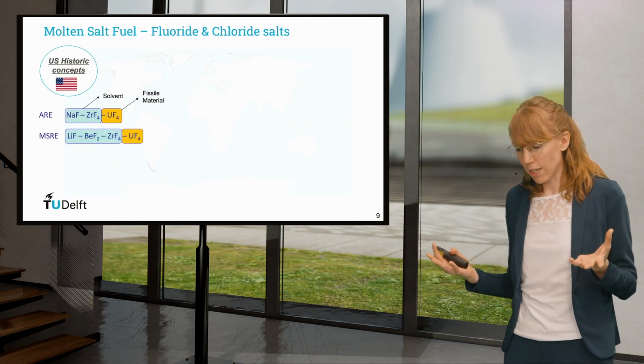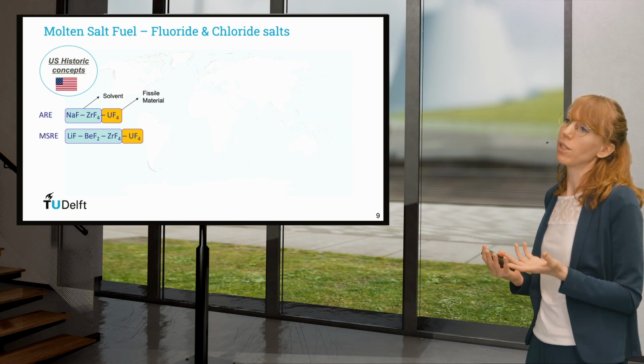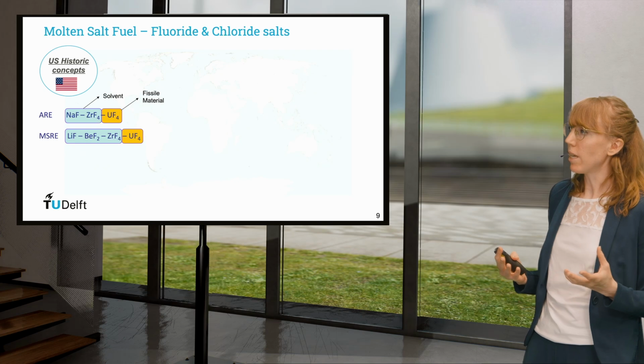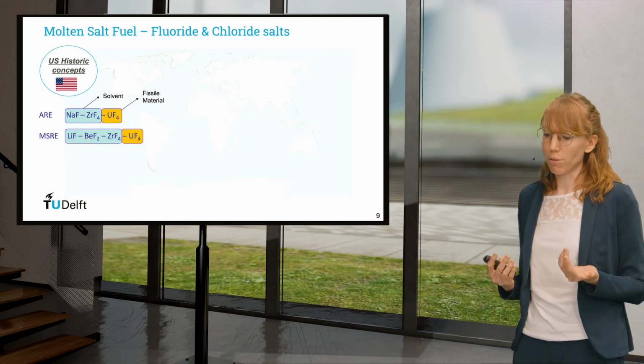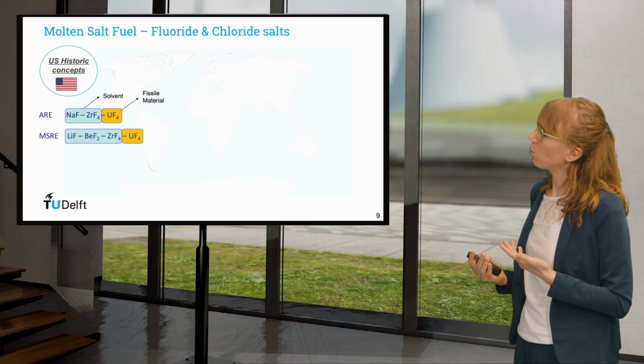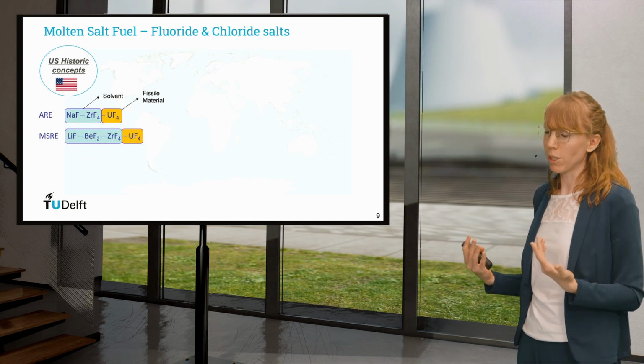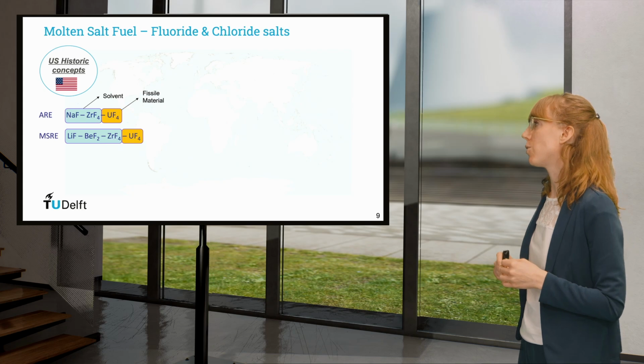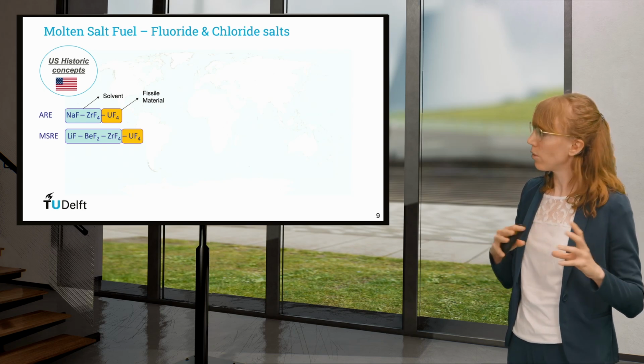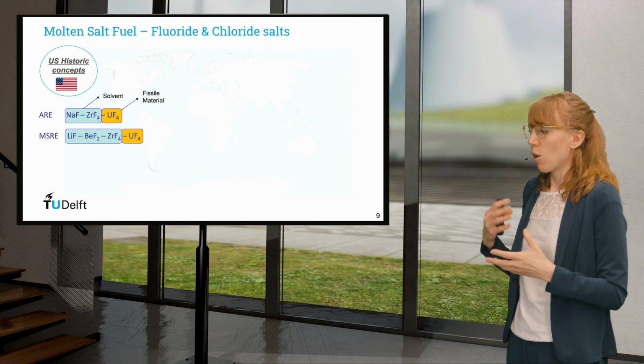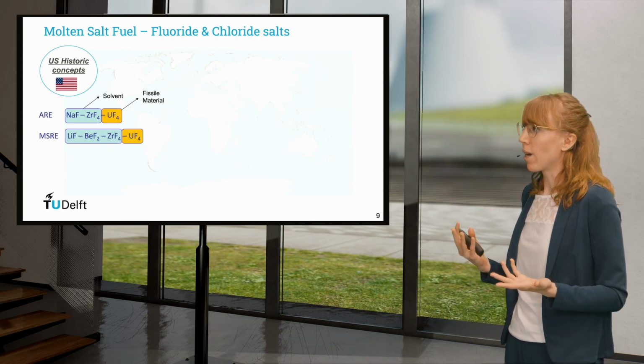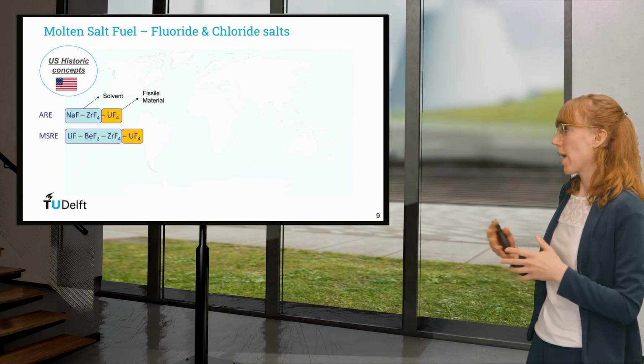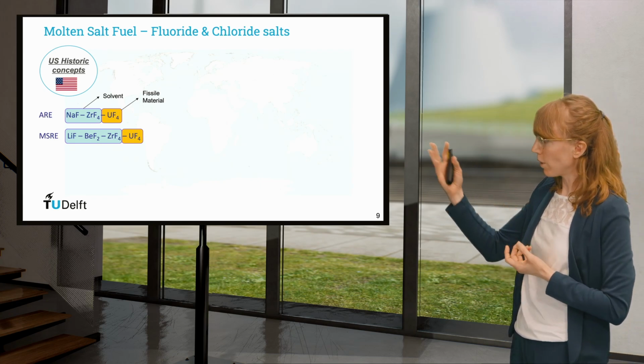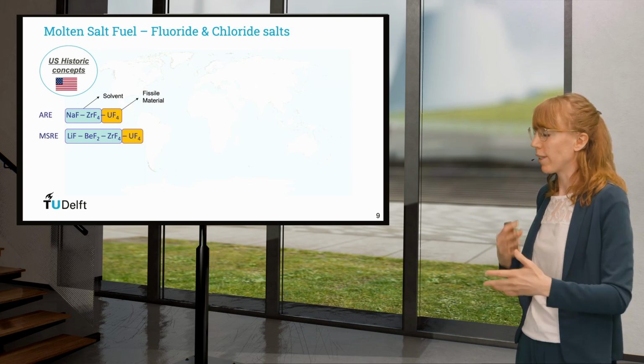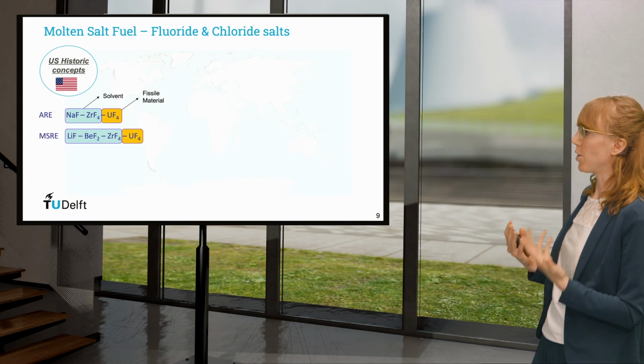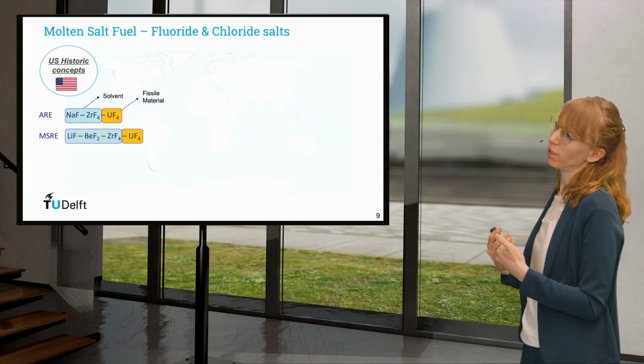So let's look first at what type of salt you can use in this kind of reactor. Historically, in the United States, for the Aircraft Reactor Experiment and for the Molten Salt Reactor Experiment, some fluoride mixtures were used, and you see them here on the slide. They are made of a solvent and a fissile material. Maybe you could think, well, why are you not just using the fissile material? If we used uranium tetrafluoride alone, this would have a very high melting point. That would not be possible for reactor operation. So we need a solvent to reduce the melting point of the mixture.